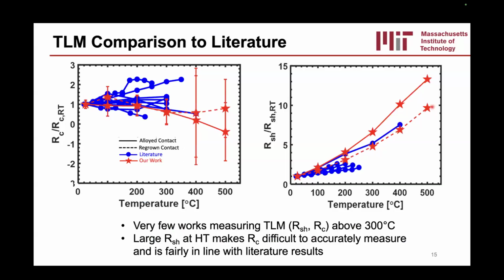We can benchmark some of this work to put it in context to other works in the literature. You can see our work here in red and literature works in blue of the normalized contact resistance, so RC normalized to the room temperature value. You can see pretty much everyone, there's a lot of work at about 200 to 300 Celsius and less, mostly because that's a typical temperature on most probe stations. That's a typical temperature you have to go to for reliability measurements. But there's not much work going beyond that. So that's what we're kind of doing here. And you can really clearly see here where the error bars significantly increase as you go to higher temperatures.